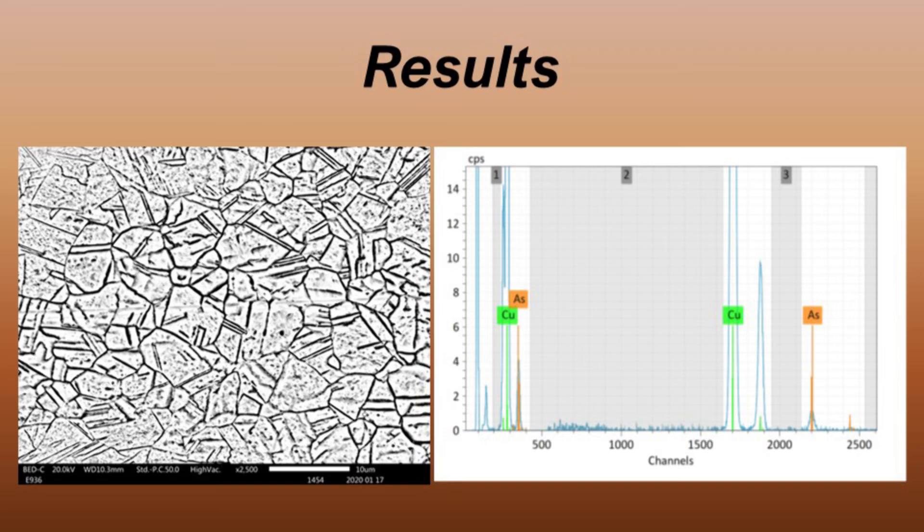Also from my work, it is possible to say that ancient Egyptian mirrors were not exclusively made of bronze, as previously stated, but of arsenical coppers also. Some of the mirrors have very high arsenic content, up to 8 weight percent in the bulk, or an arsenic enriched surface of around 30 weight percent, which means they would have been silvery in appearance rather than golden.